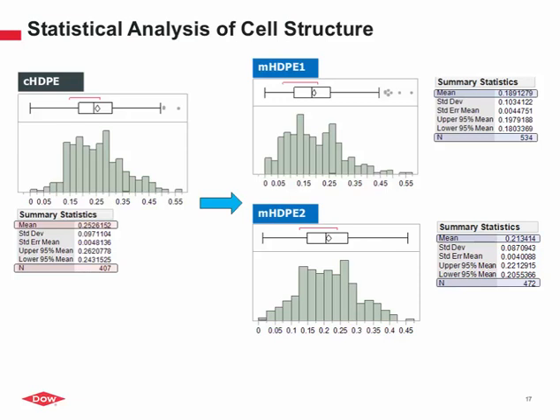What we see in the control system is a broader size distribution. The average mean cell size is about 250 microns, and the total number of cells is about 400. Comparatively speaking, for the two modified systems, the average is about 189 microns compared to 252, and in the second modified, it's about 213. For both modified, you can see it's 534 cells and 472 respectively, versus about 400 for the control. So it's a confirmation of what is seen in the images, a higher number of cells and smaller cell size, which is exactly what we were looking for.